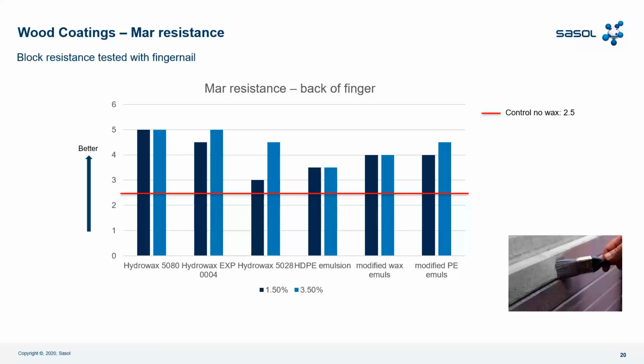Same results we got with 3.5% for 5080, a little bit better for experimental 004 and for Hydrowax 5028, followed by the modified PE emulsion at the end. The control, without wax emulsion, achieved 2.5, and you can see here that we have a much higher performance if we use Hydrowax 5080 or Hydrowax 5028, with a fingernail test.